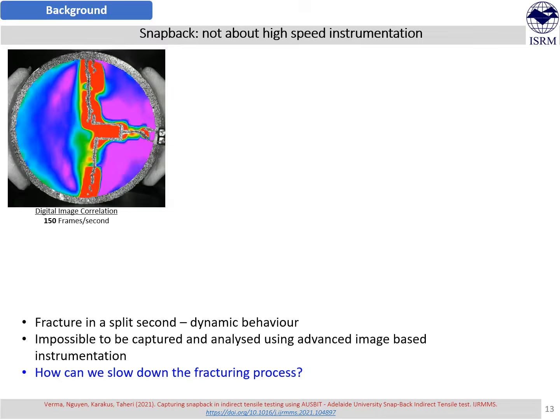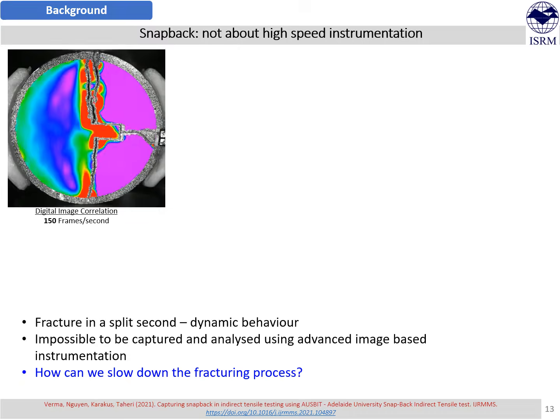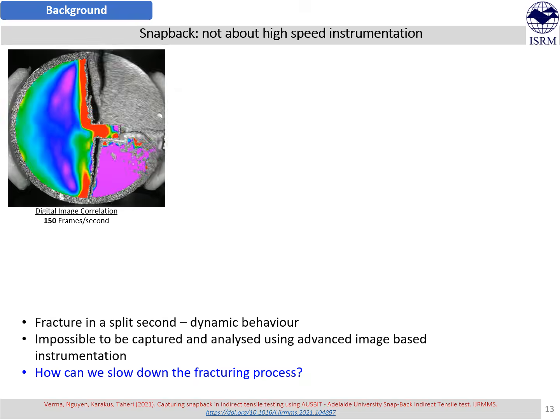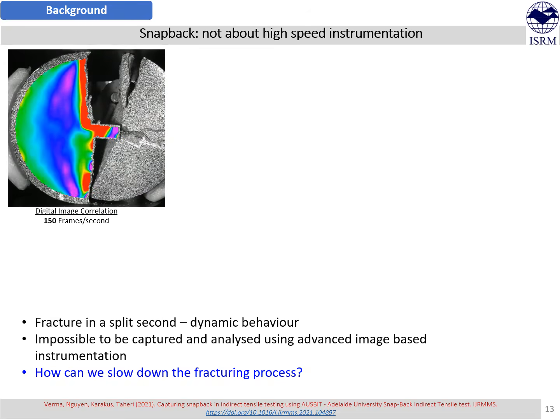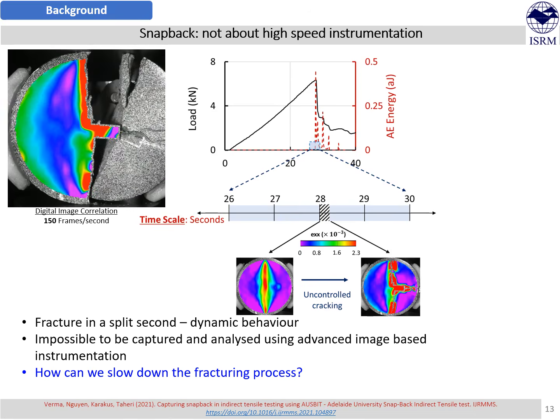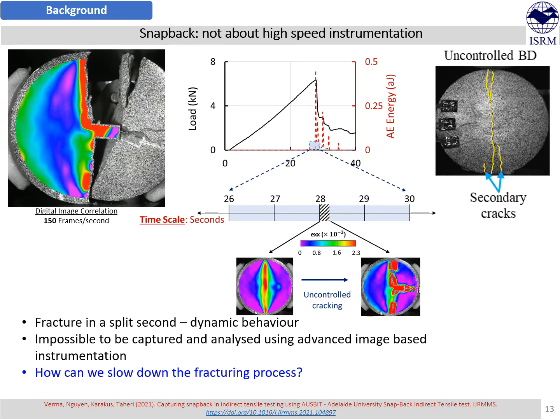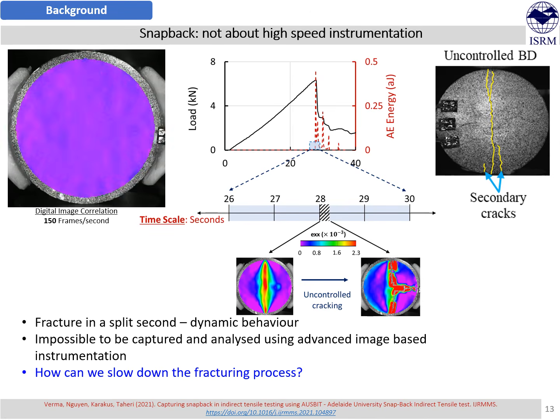As mentioned earlier, the first issue was the correct tensile strength estimation. So we started with using advanced instrumentation. We thought with a high speed camera, that is the digital image correlation technique, we can capture the local scale behavior in quantitative terms and link it with material property like tensile strength estimation. However, we realized that the disc specimen cracks in a fraction of a second, which is very quick, and we can see the cracking pattern as well, which clearly shows that the crack happens and thereafter there has been a release of excess strain energy, which might have resulted in these secondary cracks.